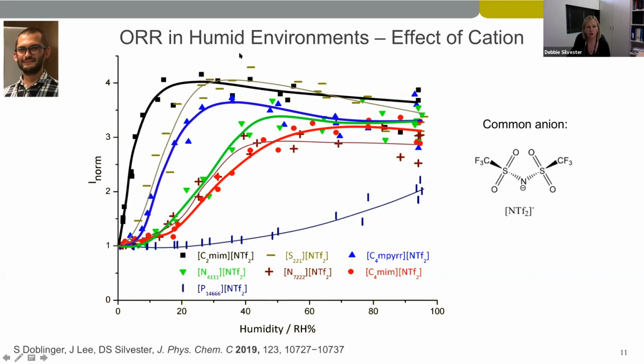It's really important to know this information, because if you're measuring oxygen reduction at different humidity levels, this is going to have a very big effect on the current response. The worst ionic liquid you can see on here is the P14666, our large tetraalkyl phosphonium cation. Here it's only above about 80% where you start to see an increase in the current response. And overall, although the cation has a very large effect at the lower humidities, at the high humidities, generally the cation has almost negligible effect.